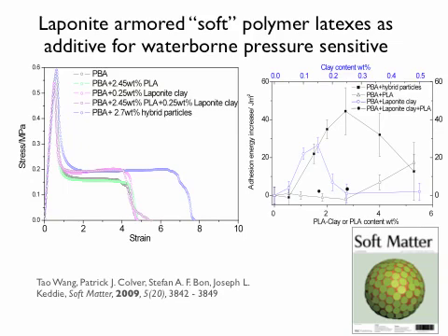So no difference whatsoever. So now let's take this polybutyl acrylate latex and add a tiny bit of Laponite clay by itself. And clay discs, imagine they interpenetrate a bit through these spaghetti chains of polymer chains, so maybe they reinforce it a little bit. And that's exactly what it does. So lift off is the same, and then you see here on the purple line that plateau level lies slightly higher. So your fibers are a little bit stiffer, but they break roughly at the same point.